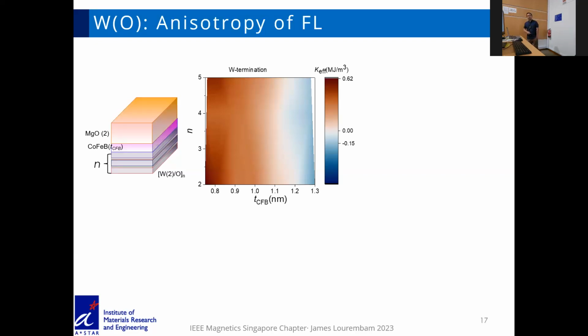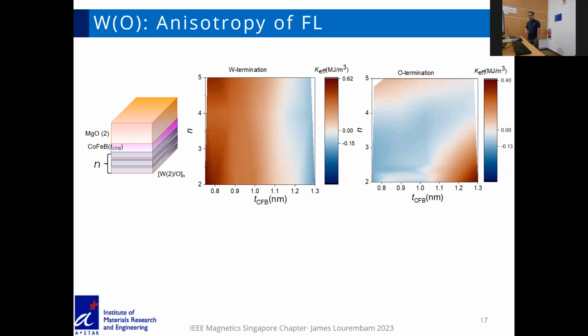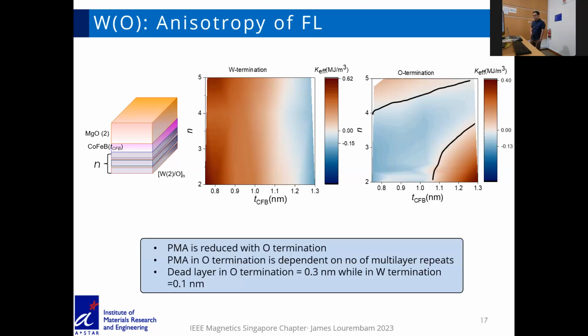Then, in terms of the half stack, we did several anisotropy measurements. We measured the K effective as a function of the number of repeats as well as the CFB thickness, and this showed the standard K effective times thickness versus CFB thickness, which means it drops as we increase the thickness of the CFB because it's coming from the interface. However, for oxygen termination, we find that the sample is actually in-plane, and it only becomes PMA at higher CFB thickness or at a high number of repeats. So the oxygen termination is not so interesting for us. And we have another issue with oxygen termination, which is that the dead layer in the system is higher than what we want.